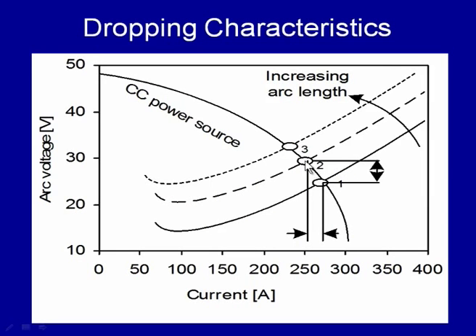This change in operating point from 1 to 2 is developed due to the change in the arc characteristic for the same power source characteristic, with the intersection of the two occurring at some other point, that is this. If we observe closely, due to the increase in arc length, the operating point is shifting from 1 to 2. Here, the increase in arc voltage with the increase of arc length is by this much, while the decrease in welding current is very marginal. This small variation in the welding current will not affect the heat generation significantly, and it will be accommodated very easily even when great fluctuation in arc length is taking place.